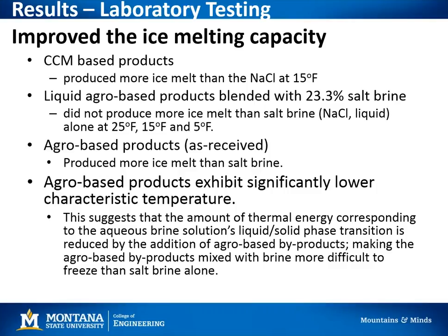And this is an interesting finding, especially when you compare it to the lower eutectic temperatures. But the agro-based products as received, or the Category C products, they did produce more ice melt than the salt brine. So there's some difference between the manufacturer-produced products and then the agro-based products that you then blend with salt brine. There's some difference going on here. But generally speaking, the agro-based products exhibit significantly lower characteristic temperatures. So that's that eutectic data that we looked at.